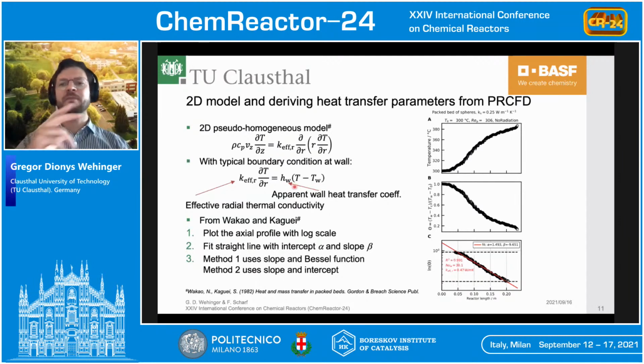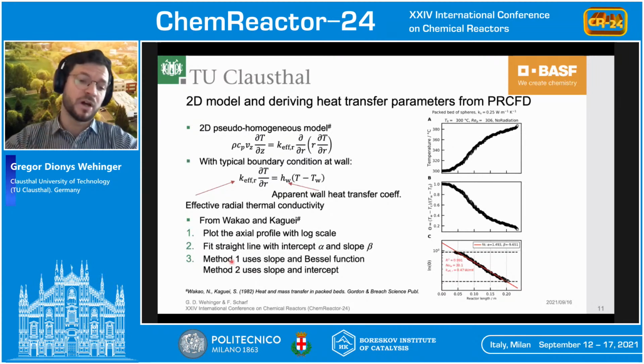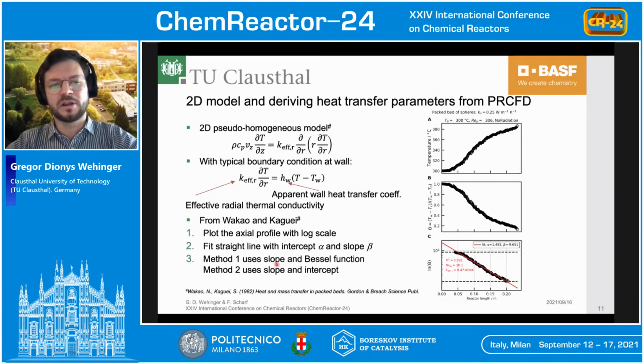So we now derived from our PRCFD simulations these 2 parameters, K effective R and HW, according to a method suggested by Wakao and Kaguei in the 1980s, where we plot the axial profile from the CFD simulation, as you can see here, in a logarithmic way. And then we fit a straight line to a certain amount of this curve. And finally, we have a slope and the intercept. Depending on method 1 or method 2, we use the slope and a Bessel function, which I skip here. Method 2 only uses the slope and the intercept. So both methods I will compare in the next slides.